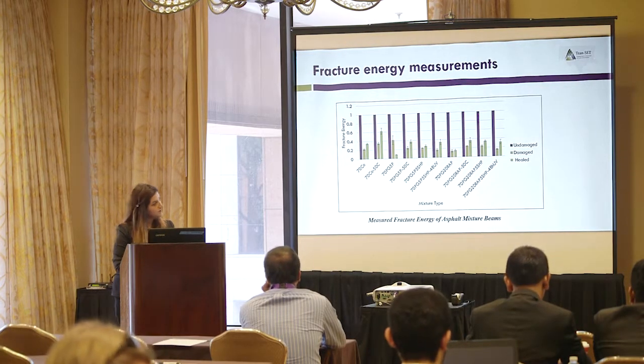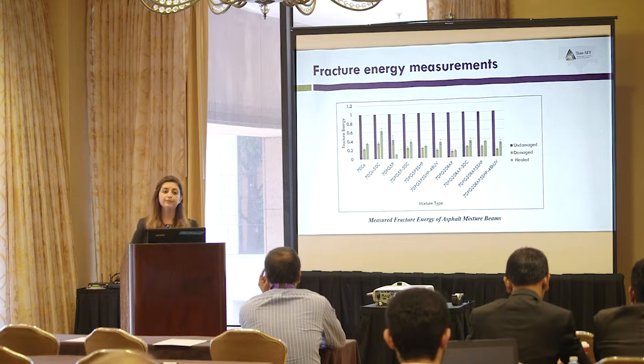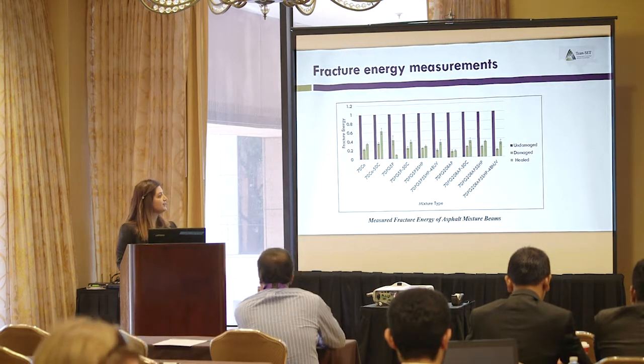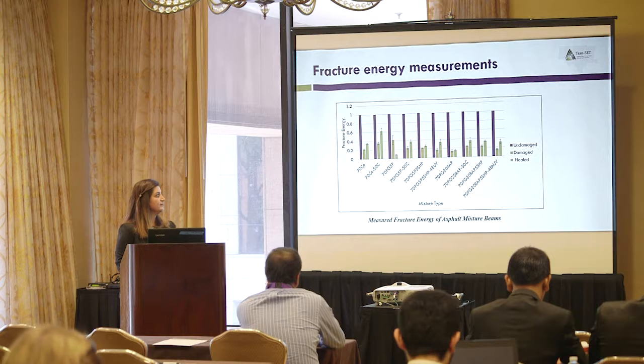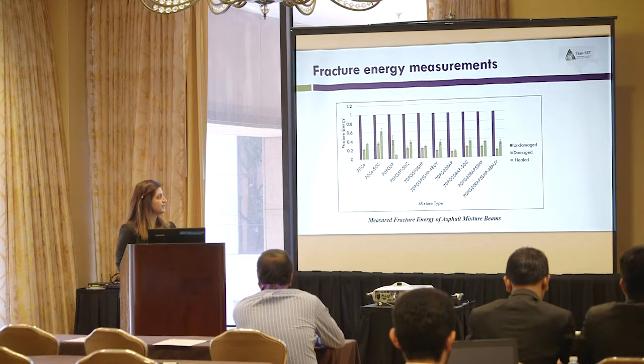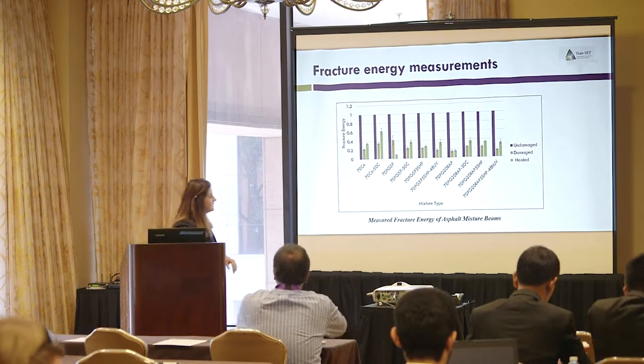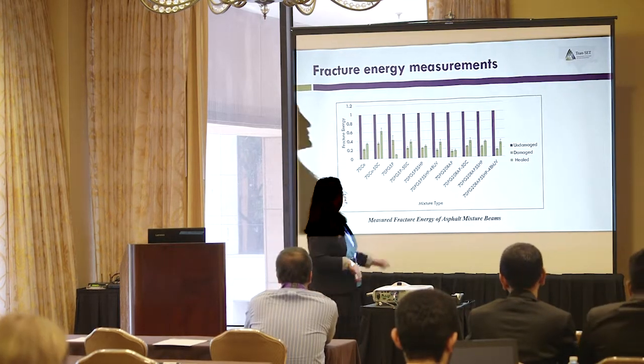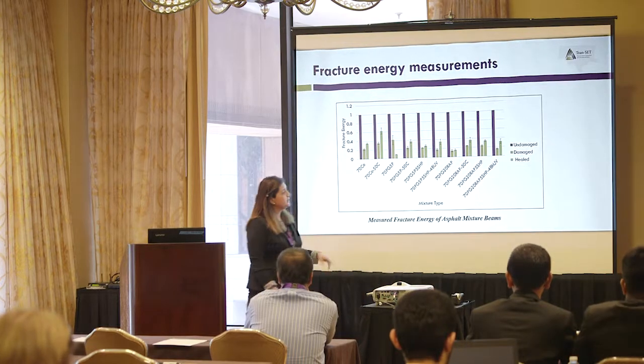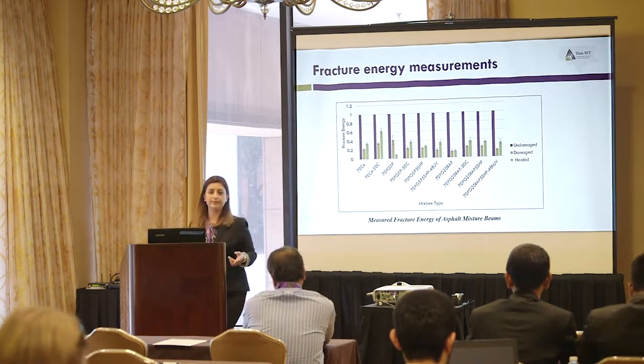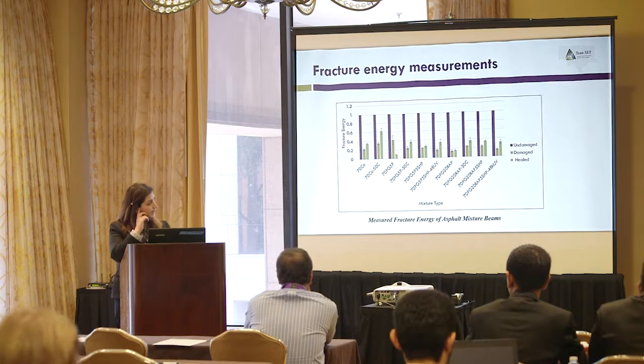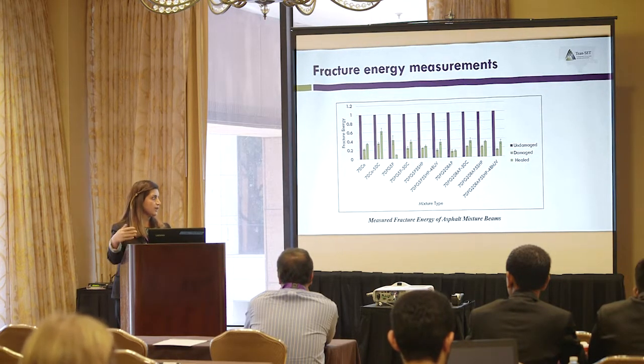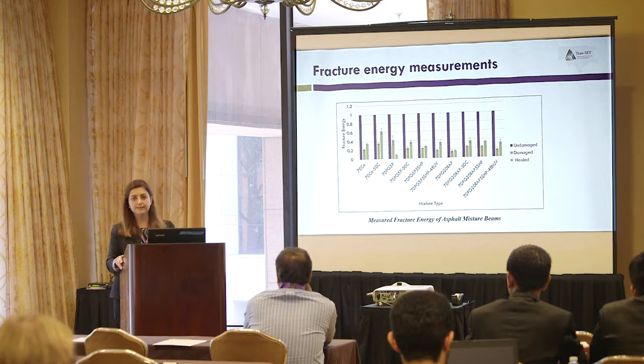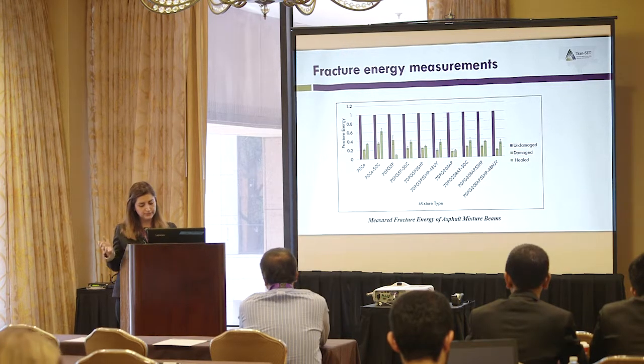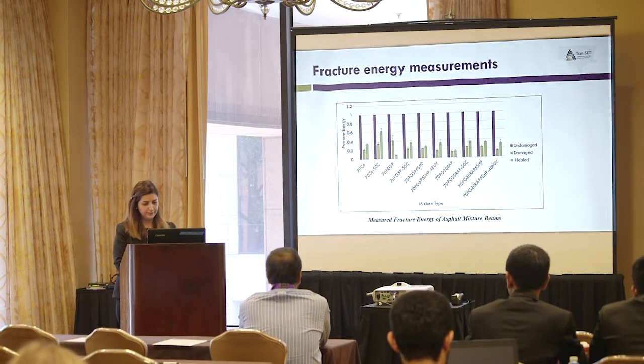This slide shows the result from the fracture energy test we performed for different mixtures with and without recycled material and self-healing polymer. Again, as you can see, we showed the same trend in this slide. We have self-healing polymer, and then we have self-healing polymer with the UV light exposure, and the results were improved with adding self-healing polymer and then exposing samples to UV light for 48 hours.